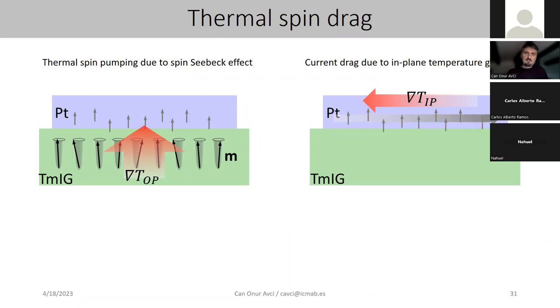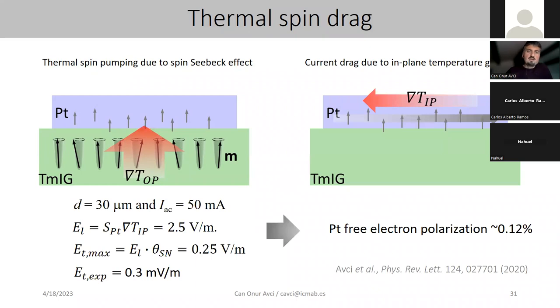And then you have the final inverse spin Hall effect voltage coming in the third direction. So that is basically an effect that was not known before, and that we call the term spin drag. And then they put in some numbers such as the Seebeck coefficient and the Nernst Hall angle, etc. So we expect this platinum free electron polarization to be on the order of 0.12%.